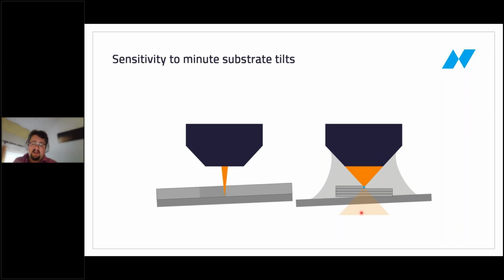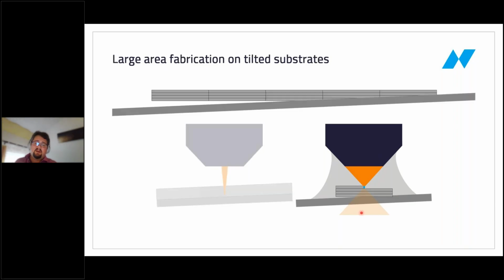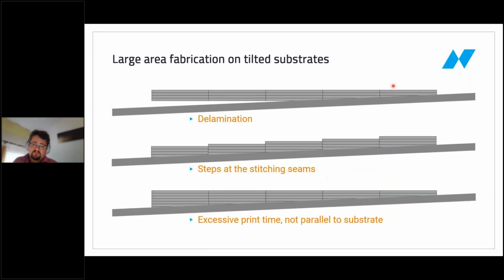This is bad enough on a single structure, but if you want to make something that's larger than a single print field, then you run into even more trouble. In this case, you can clearly see that if you just measure the height once and you print at the same height everywhere, then in some region you will lose most of your structure, whereas in the other region you will have a complete delamination. And this is a mechanical problem waiting to happen. This will eventually just get disconnected from the substrate, and then you don't have a printed structure anymore.